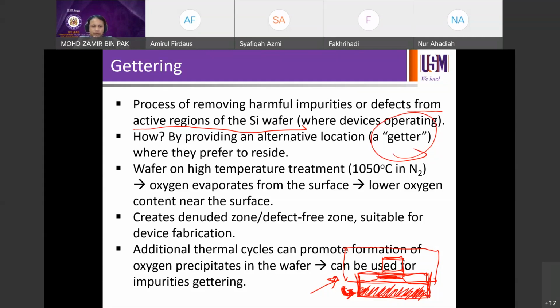So the wafer goes through a high temperature treatment, typically around 1050 degrees in nitrogen ambient, in order to perform the gettering process. Oxygen evaporates from the surface, leaving low oxygen content near the surface, and this creates a denuded zone or defect-free zone suitable for device fabrication. I'm going to share some details on the gettering process later on. Additional thermal cycles can also promote formation of oxygen precipitates in the wafer, which can be used for impurity gettering. So oxygen precipitates also help to improve the gettering process. That can be done as well.